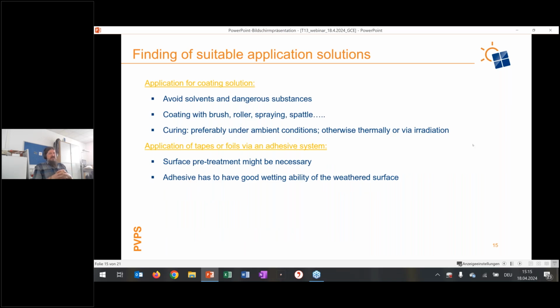Additional requirements, especially when we repair in the field: we want to avoid solvents and dangerous substances. We need to be able to apply the coating with a brush, a roller, spray, or other means, and the curing preferably should really work under ambient conditions. Otherwise, the effort is increasing. Next to the coatings, we also looked into application of tapes or foils with a pressure-sensitive adhesive. And here, again, the surface must be clean, and probably we need a surface pre-treatment in order to increase adhesion. And we also need a good wettability of the adhesives. So these were the requirements.